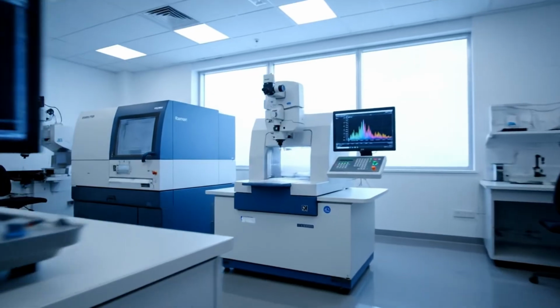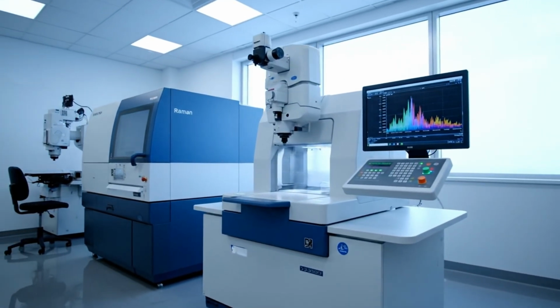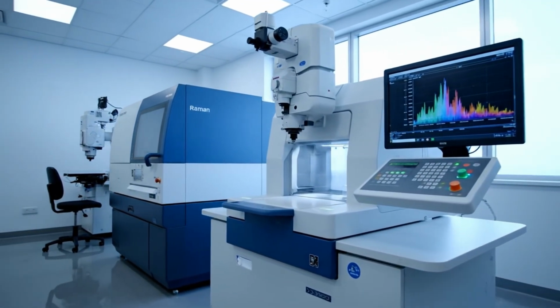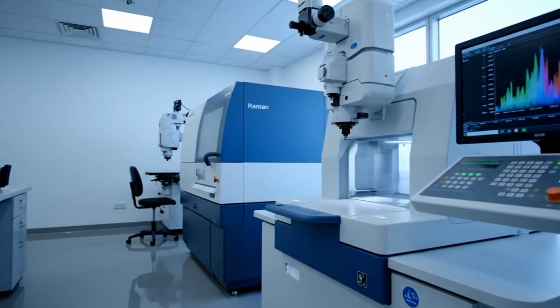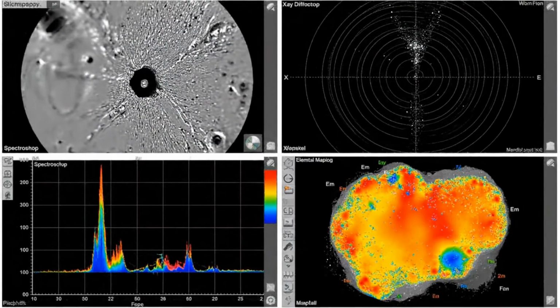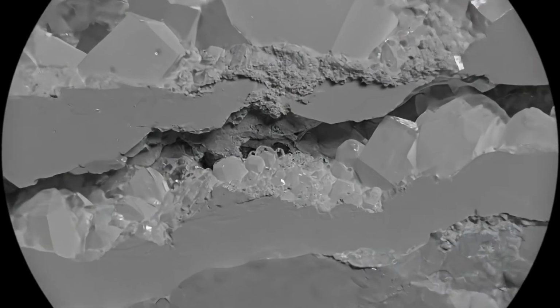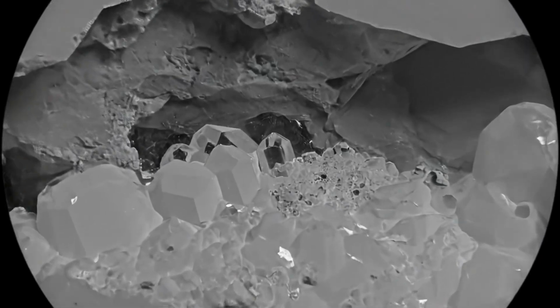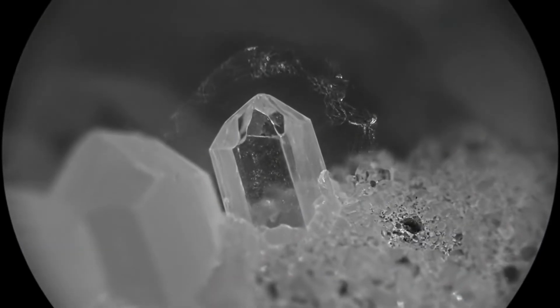But proving this required technology Romans never imagined. In 2023, MIT researchers used 4 different analytical techniques to examine lime clasts at the molecular level. Scanning electron microscopy revealed crystalline structure. X-ray diffraction identified specific calcium compounds. Raman spectroscopy confirmed the self-healing calcium carbonate in healed cracks matched the lime-clast composition. Elemental mapping showed calcium flowing from clasts directly into cracks, like blood vessels supplying healing tissue.